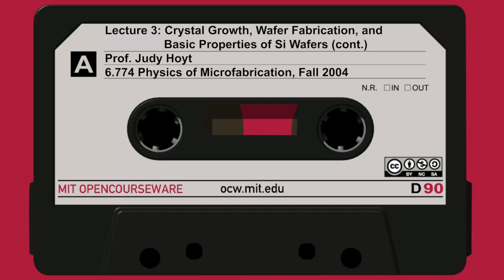Let's go on to slide 5. In fact, let's talk about a couple of different ways we could take a perfect crystal and form these defects. The simplest way, and the way you would probably imagine if I asked you how to create an interstitial and a vacancy, is that I just pull a silicon atom, rip it out of its lattice site and stick it somewhere as an extra atom. Then I have a vacancy where the atom was left behind, and I have an interstitial. In fact, this vacancy-interstitial pair is called a Frenkel pair.